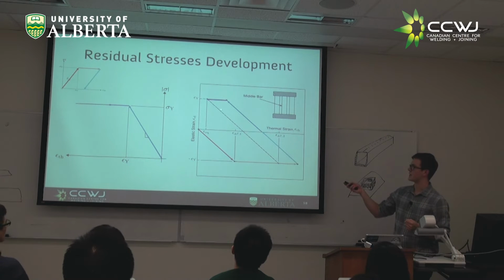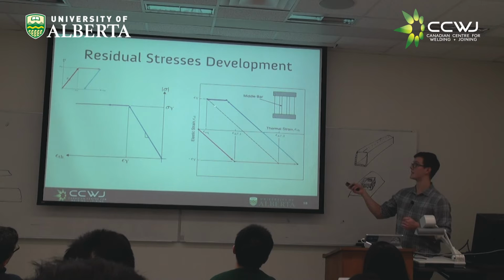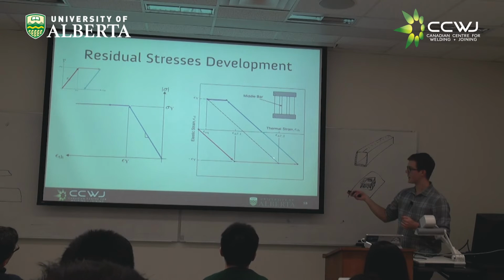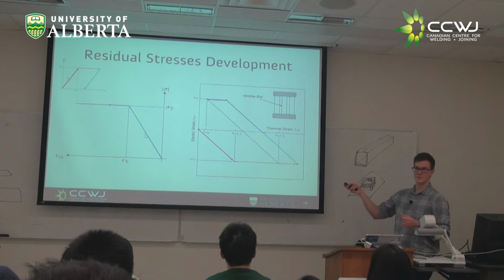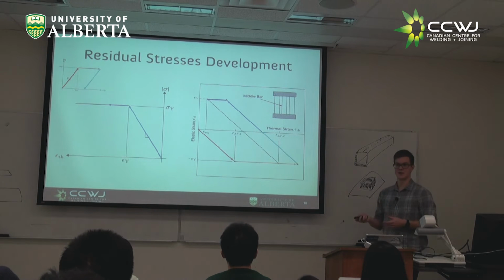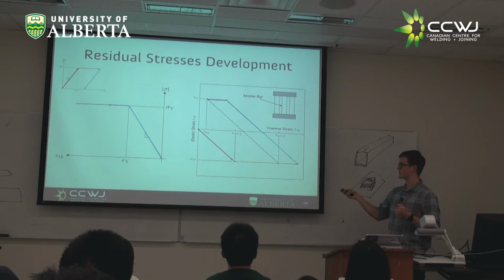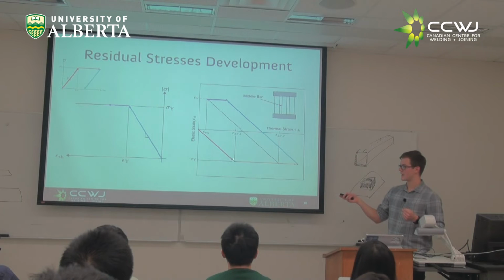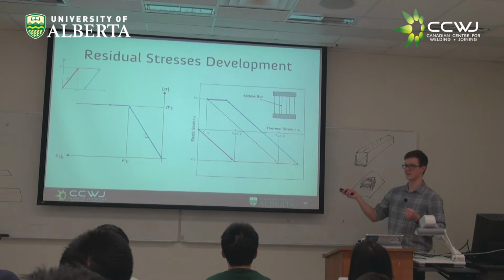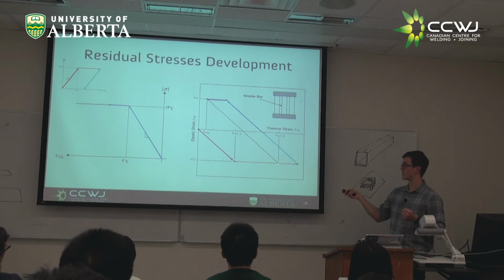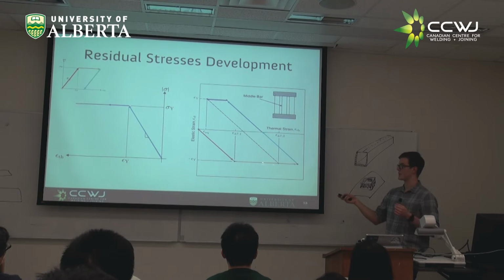Now the other dashed line I've drawn here would be where you have yield level plastic strain, or yield level elastic strain, or yield level stress upon cooling. So really all of what we're worried about in residual stress is going to happen between these two points. Any heating beyond this point, the residual stress is pretty easy to predict, at least in the simple model. It's going to be yield level. It doesn't matter how much additional temperature you add beyond this point, our elastic strain, our stress is not going to change. So really what we're trying to understand is how wide is this point where we start developing plastic strain? How wide is this point where we develop yield level stresses upon cooling? And if we know those two widths and we have an idea for what's going on between those two widths, we can predict the total residual stress we're going to have.